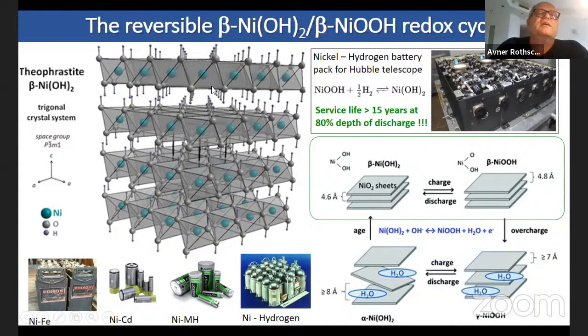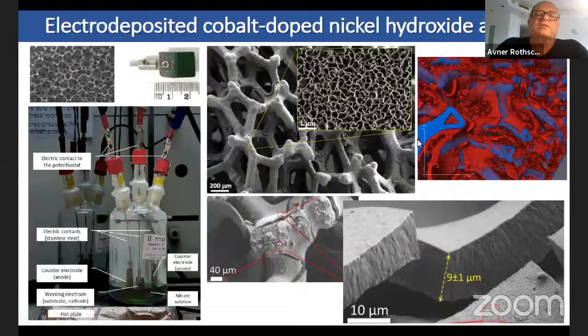I showed before. And if you look at what really happens here, this is the crystal structure of the nickel oxyhydroxide system. So you have nickel O2 octahedra with equatorial hydrogen on its oxygen. On the other phase, on the charge phase, you have equatorial hydrogen only on every other oxygen. So basically the discharging reaction occurs by diffusing of protons in and out of the lattice, where eventually the proton reacts with hydroxide ion to generate water at the surface. So obviously the charging and the discharging reaction is limited by solid state proton diffusion with these layers, which is why making nanostructured material is very important.